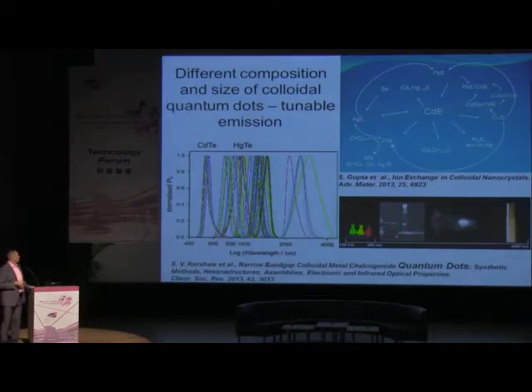One way to tune emission of colloidal semiconductor nanocrystals is by doping. And this can be done by ion exchange, which is schematically shown here. So we start from cadmium chalcogenides, for example, and then we introduce mercury ions, we introduce different other cations, and by that we can tune emission of these nanocrystals alongside with the change of size, as I mentioned on my previous slide, and this is what we are aiming at.